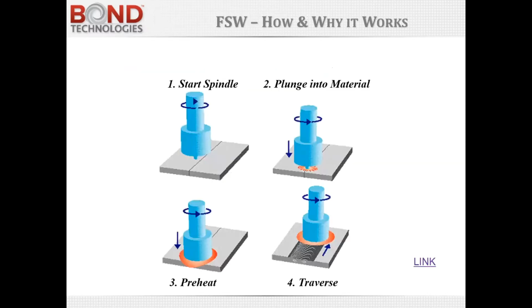So the basics: we're using frictional heat with this tool, shown in blue, to cause material to plasticize. Picture a milling machine, a vertical mill, with this tool in it that consists of a pin and a shoulder. In step one, the spindle starts rotating. In step two, the pin, which protrudes below, plunges into the material. In this case, we have, say, two aluminum plates butted together. As the pin contacts the material, frictional heat causes it to plasticize, and the pin plunges into the material.